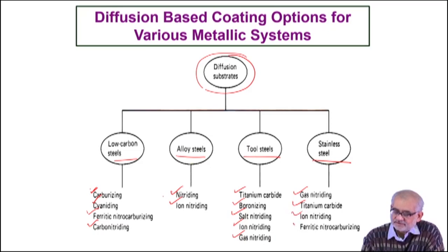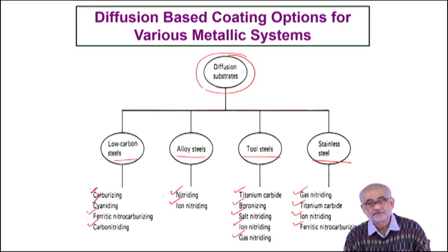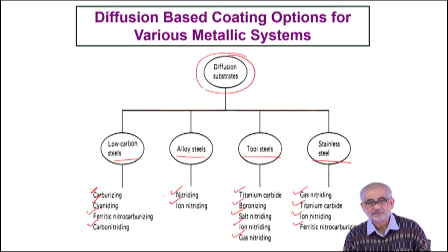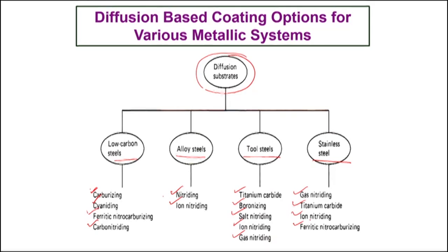What is the relevance of bringing all these subjects together? They are all based on interstitial diffusion processes, and they are also diffusional processes — hence they can be called diffusion coating — but they have their own names like nitriding, carburizing, and carbonitriding. Whenever one talks about diffusion coating, typically we are talking about chromium, aluminium, and silicon, which have very high affinity for oxygen and the process is through substitutional diffusion, with the application usually being high temperature protection. The other processes — carburizing, nitriding — are not necessarily for high temperature protection but for room temperature or slightly elevated temperature resistance to wear and tribological purposes.